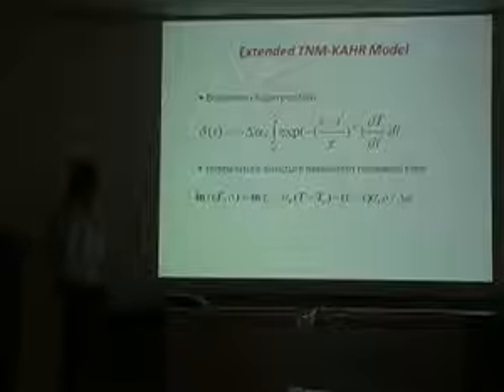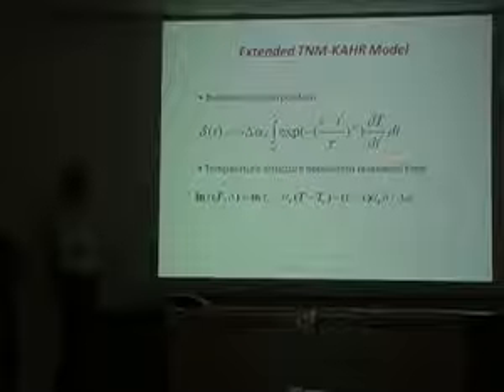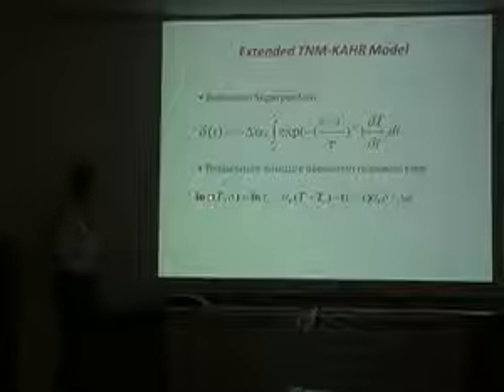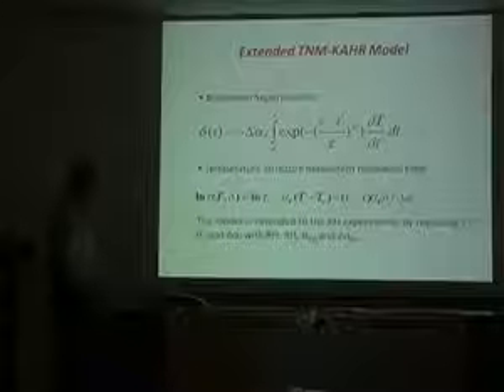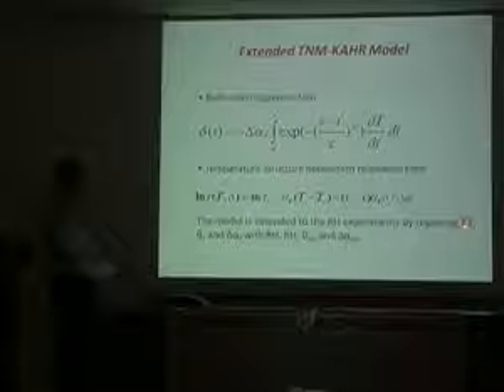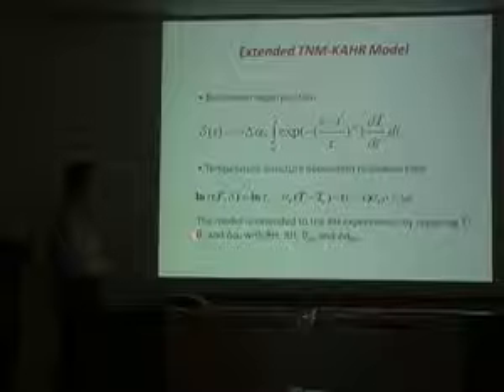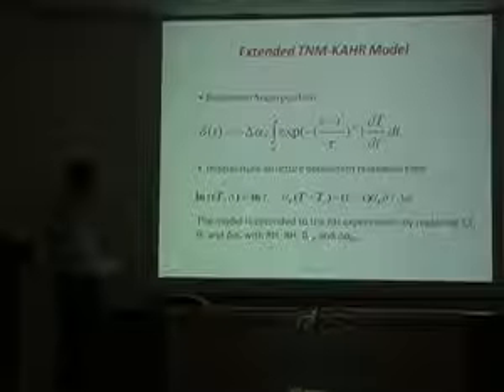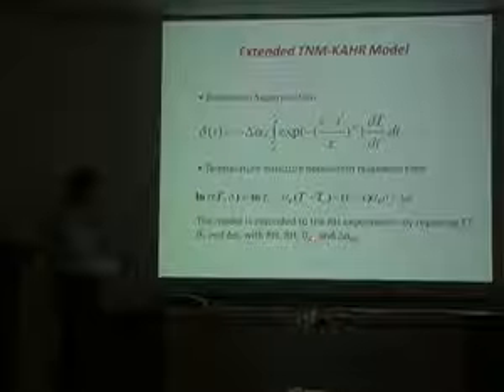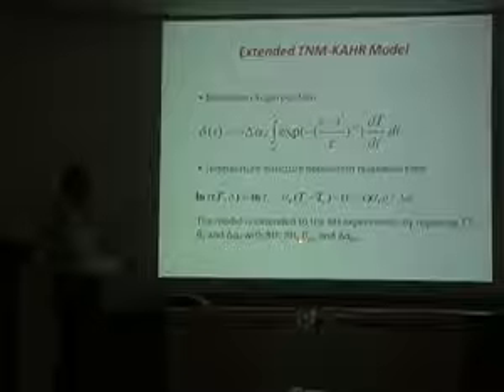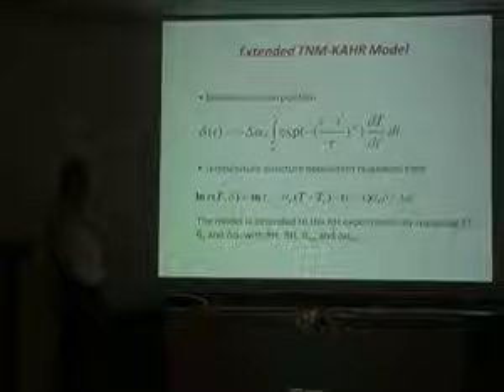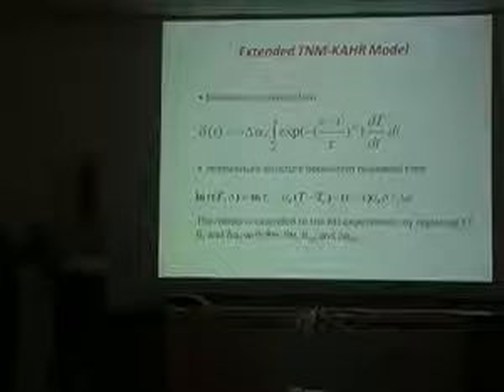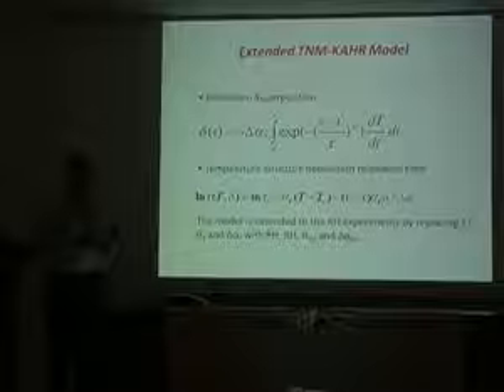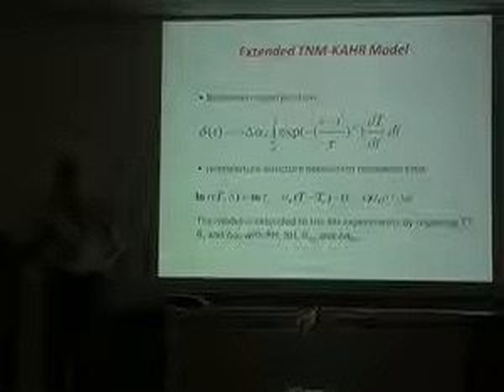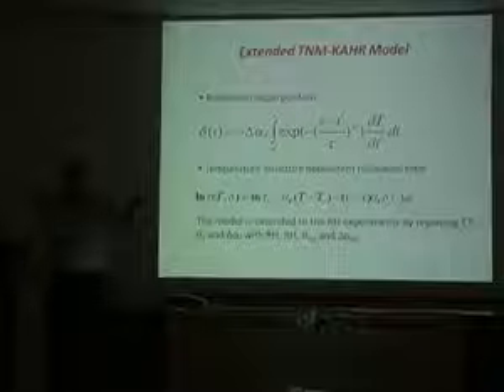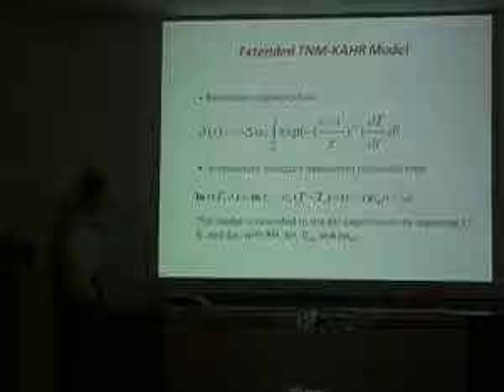So we also tried to fit the data using the TNM-KAHR model type of behavior, and instead of using temperature, we extended it to relative humidity by replacing the temperatures and activation energies with relative humidities, an activation type parameter, but that's related to relative humidity effects on the mobility and the delta alpha RH. And it turns out the fits were about the same as if you did it for a temperature jump. So I'm not going to show the details of that. But they were about as good. But the parameters were really different. Okay? Because why? The relaxation times are looking different and the dependencies are different. So it's actually looking different.